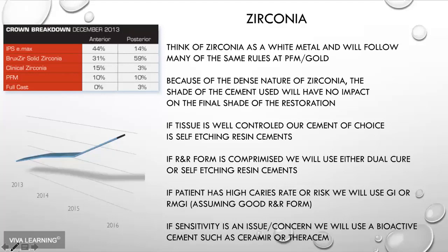If the retention and resistance form is compromised, now I may go to a dual cure resin cement, though a self-etching resin cement is still an option. The difference between the two is that a dual cure resin cement is clinically proven to have higher bond strength to the tooth and to the restoration than a self-etching resin cement. So if I have a really short clinical crown and my retention and resistance form just is not good, and I have no other choice,